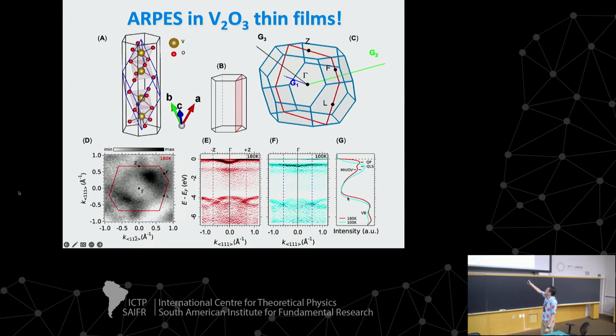We measured our data in this plane of reciprocal space, and one of the reasons we did that is that we wanted to decouple as much as possible antiferromagnetism, whose vector lies in the basal plane, from electronic structure changes. So we measure in this plane in reciprocal space that corresponds to, this is the hexagonal conventional cell, this plane in the real Brillouin zone of the system.